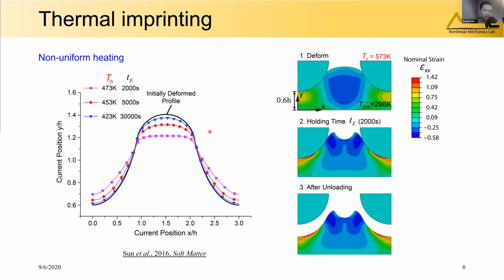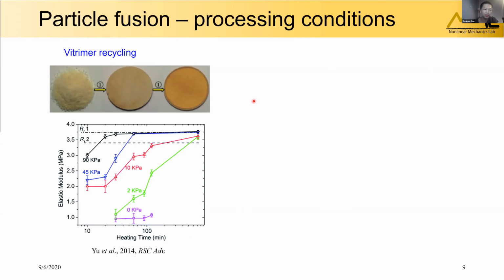If we use a much lower temperature but long heating time, the final profile can be very different, look at this blue line. The heat conduction is relatively fast, so the final imprint can be very close to the initially deformed profile. So this is for the bulk thermo-mechanical behavior of the Vitrimer. So now we go to the particle fusion.